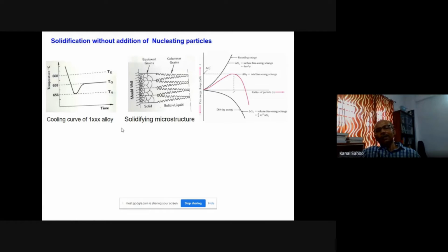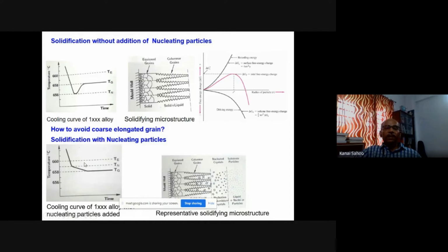Now, how to reduce this undercooling? How to avoid this elongated grain structure in homogeneous nucleation? See, here 660, but nucleation is above that temperature. Earlier I showed you 4 degrees, here 2 degrees. Now you will see some cases where nucleation will start really at high temperature. So if you can do that, the entire melt together at the same time, you can start your nucleation and growth, so that there is no time for the elongated grains to develop.